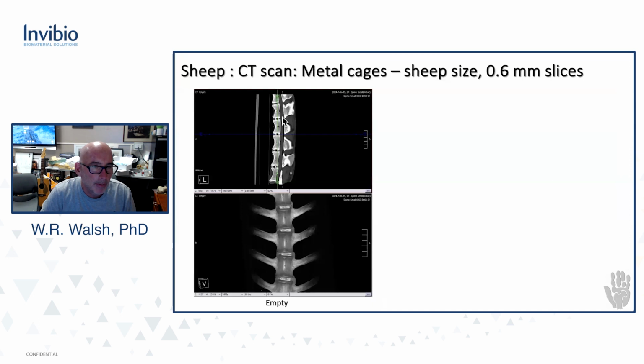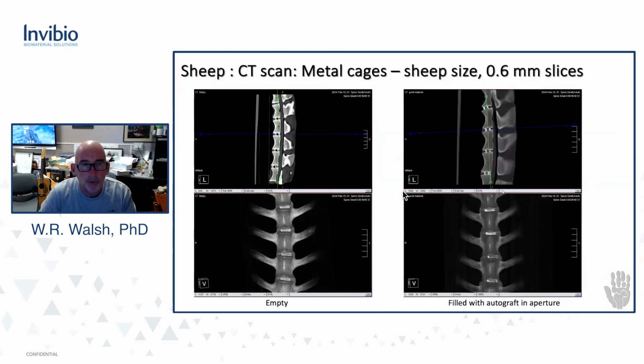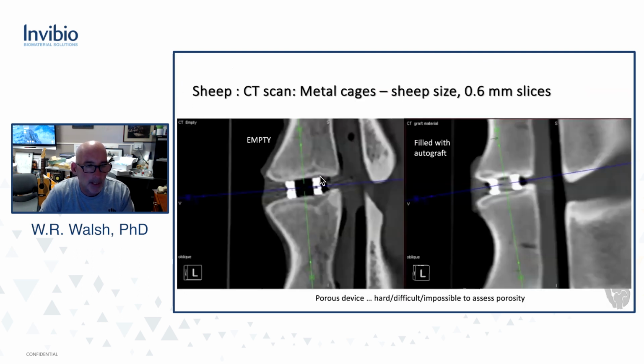And you can see black is an air ball because it's actually air. And then we filled them up with graft and did the same exact spines. And if we go a little bit closer to that, this is what empty titanium looks like. This is one of the implants. They all look the same because you can't tell. And this is it filled with graft. I really can't tell what implant it is. Is it porous? Is it not porous? I can tell that there's something in there, but I really can't tell the quality. So it's hard to assess porosity. It's also hard to, this is time 0.